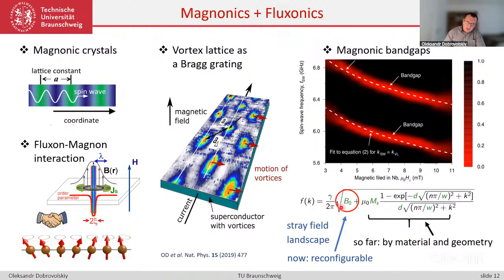And what we have been exploring during our studies is to use a stray field landscape, so biasing or effective field, which results because of the vicinity to the superconducting layer. And since the vortex lattice parameter can be tuned by tuning the strength of the applied magnetic field, that means that also the field and its modulation and periodicity can be tuned, and this allows us to introduce reconfigurability. So basically, an Abrikosov vortex lattice in a superconducting layer behaves as a reconfigurable, tunable Bragg grating for the propagation of spin waves.